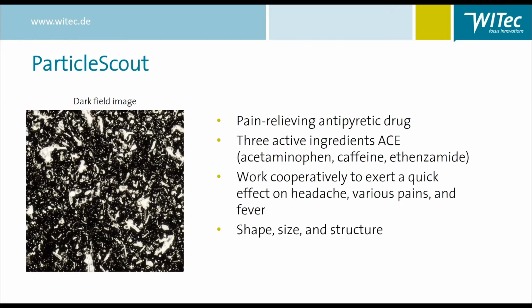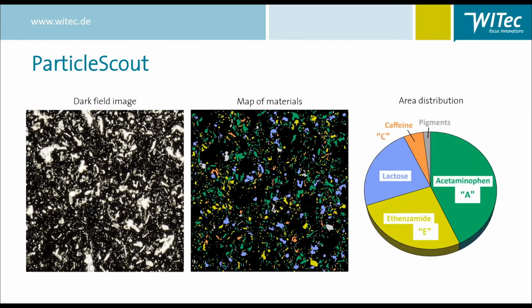Criteria were then selected that focused the further analysis on particles with a maximum diameter of less than 100 micrometers and an area of 1 square micrometer or larger. This highlighted a total of 3,052 particles. A Raman spectrum was then acquired from each particle in an automated way, followed directly by the chemical identification with the integrated TrueMatch Raman spectral database software.